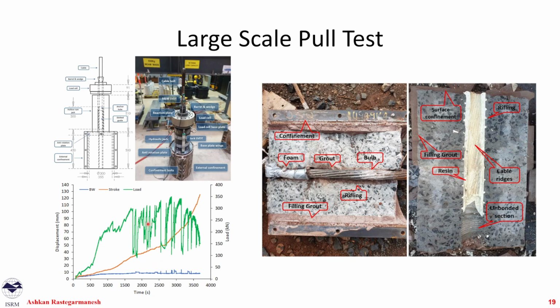This green line was a load cell over time, the value that we would get. Typically, we had a load pickup, and then we get to a peak value, and then we had oscillations. Each of these oscillations was accompanied by a very loud noise and a jump of the sample. This orange line is the stroke, like how much vertical displacement, how much pull-out happened. And this small blue line is basically the movement of the LVDT at the barrel flange.